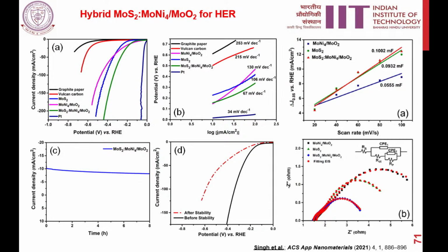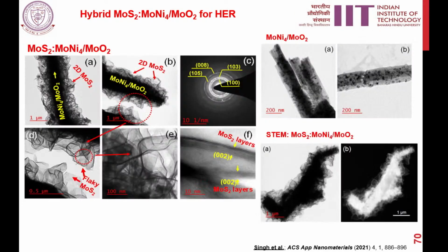So we see the catalytic activity, like Tafel slope, we got 67, which is close to platinum, which is standard platinum, which is 34 for the hydrogen evolution reaction. Second thing, the moly nickel surface. You go back. Let's go back.